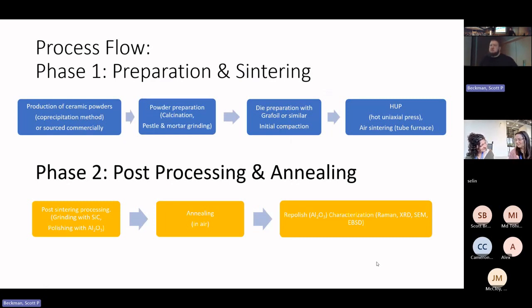And then once we have our powders ready to work with, we then pack them into a die of some sort. We have both the die in our hot uniaxial press, which is a carbon die, and we also use a stainless steel die at times that we just use in a normal pellet press to produce what you call our green body pellets. And then after we produced our somewhat densified green body, we then use hot uniaxial pressing or just vacuum sintering to try and densify the product further. And then once we've completed that, we do some post-sintering processing, primarily annealing, and then we also do polishing and grinding to try and remove surface defects and things away from that. And then after that, we can finally do our analysis to see what we've actually produced.